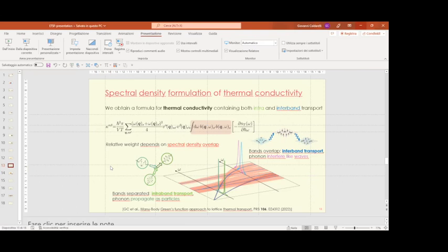Yeah, there is a really interesting question. The idea is that the velocities are not changed by the interaction, and the dressing of the self-energy follows from our approximation, our dressed bubble approximation. In fact, you can interpret this formula as basically a bubble in which you have two bare vertices, the velocity vertices, and then this part here consists of the phonon propagator. So in order to treat the velocity and consider a generalized non-quasiparticle velocity matrix, you would also have to consider vertex corrections to the phonon bubble that you compute in order to consider thermal conductivity.